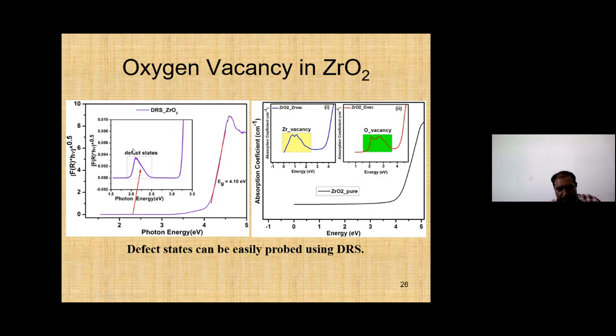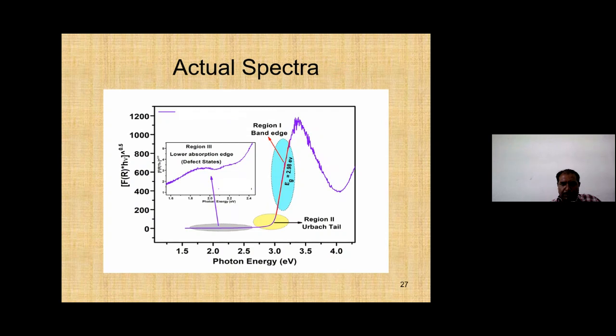Once again you can see this particular data, where there is a state between 2 to 2.5 electron volt. So you can not only quantify whether you have a defect state or not, but you can also predict whether this particular defect state is due to zirconium vacancy or due to oxygen vacancy. So it's really a powerful tool. What I want to convey to you is that it's really a very powerful tool.